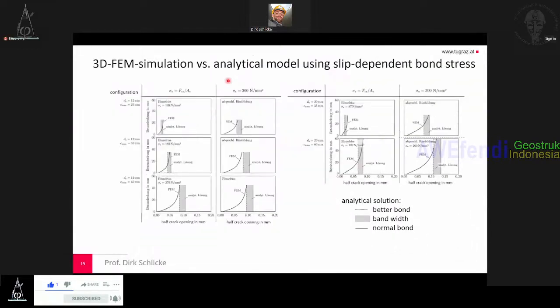And if we start to change the configuration, so we have different diameters, different concrete covers, we also see that the analytically calculated crack width refers rather to the surface crack width of the FEM simulation than to the crack width at the reinforcement bar. Overall, the analytically determined crack width refers to the surface crack width independently from the concrete cover. And this is very important because all our codes have an additional cover effect. If you remember, there's some additional cover term in the slipping length determination, which is in fact not mechanical. This is only due to the statistical variation and falsification of the bond stresses in the calculation formulas. So in fact, we have no additional effect of the concrete cover on the crack width.